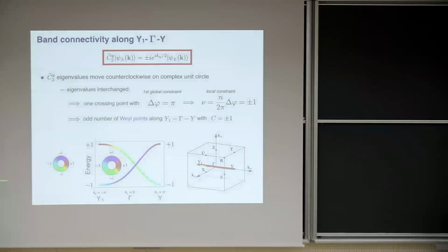So what we have found is that any material which has the screw rotation symmetry must have an odd number of Weyl points on this axis.